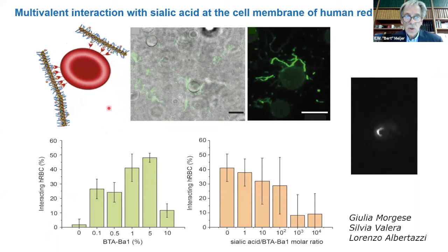Here you see the cartoon, what you hopefully see in this fluorescent microscope picture over here, or even better here. What you now see, this is the cell. This is a supramolecular polymer. And what we see is that it really goes in patches. Patches here, patches there. And if you look at the movie, you see that certain parts of the fiber are really connected to the cell, while the other part is still moving around freely. And it is our proposition that the cell, with its specific position of sialic acid, will recruit those parts of the supramolecular polymer to bind strongly. And that would be the ideal multivalency behavior, similar as in nature, the two fragments are coming together.